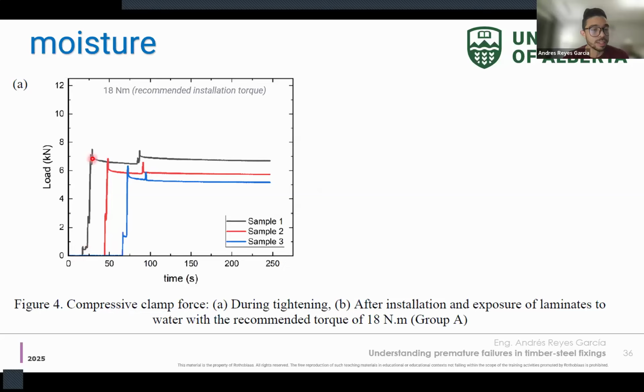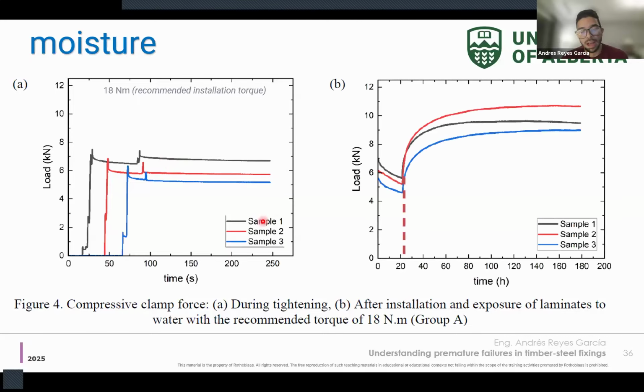Right when we install it, we give it the recommended installation torque, which is more or less 18 Newton meters for this screw. So with 18 Newton meters, we give the screw more or less 7 kilonewtons. So we start with that stress. We have an immediate relaxation of more or less 1 kilonewton, and then we hit more or less a plateau right here, around 7 kilonewtons if we take a look at the black curve. And then at 24 hours right here we add water to the sample. So what you see here, after 1 day we put some water. So this seems to be a horizontal curve, but actually it will tend to decrease a lot. So we have an initial relaxation, and this is very, very relevant, of more than 1 kilonewton for the screw.